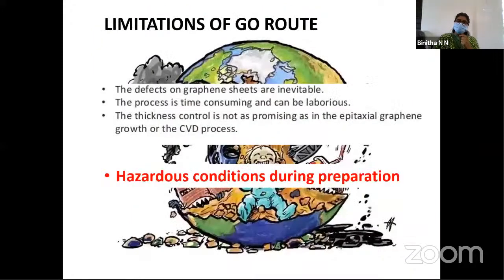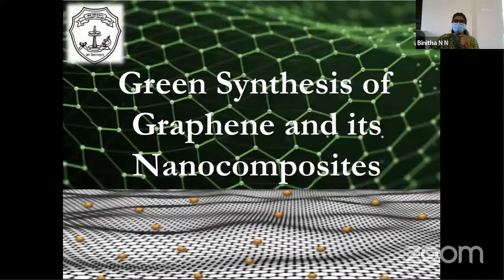So we cannot apply it for applications where green chemistry is relevant, for example, for pollutant degradation, for pollutant sensing, etc. It is not ethical. It is also not so good for sustainability. So the defects of the graphene oxide route are the defects on graphene and the functionalities on graphene, and sometimes the thickness may not be as good as that of CVD or epitaxial graphene. And overall, the process is very hazardous. So we need some green synthesis for graphene and its nanocomposites.